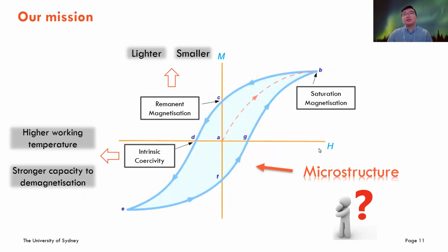What you can see here is a typical hysteresis loop with the applied field on the x-axis and the magnetization on the y-axis. The first important point is point C, which is called the remanent magnetization, which represents how much magnetization is left when the applied field H equals 0. It strongly affects the magnetic energy stored in the magnet. So the higher this point, the lighter and smaller the magnet will be.